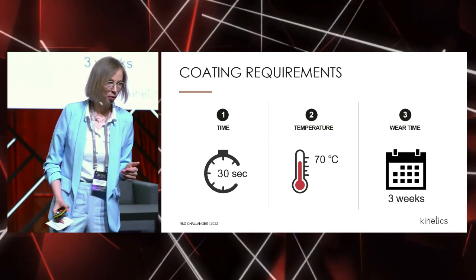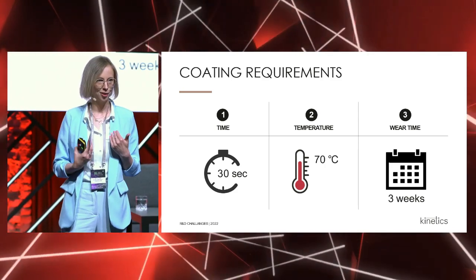The second requirement is temperature, because the substrate, us, humans, are really temperature-sensitive substrates. And when the temperature reaches higher than 70 degrees Celsius, it can become painful. The third specific requirement is wear time. In all industries, all coatings are developed with the aim to have good adhesion and good durability. But for natural nails, we still need good adhesion, but the durability should be only 3 weeks. And after 3 weeks, the coating should be easily removable.